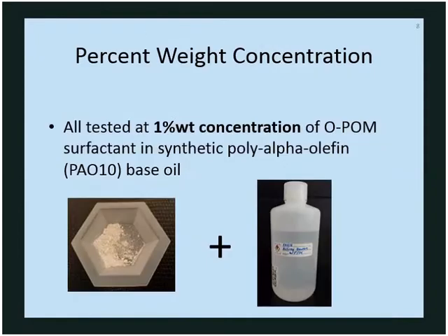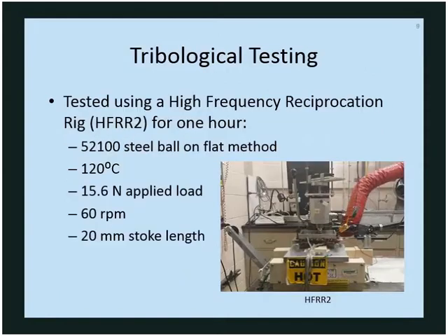Varying percent weight concentrations were used. However, they were all tested at a 1% weight concentration of OPOM surfactant in synthetic polyalphaolefin base 10 oil. Tribological testing was done, and tribology is the study of friction, lubrication, and wear, particularly within engine systems. And that was done using this high-frequency reciprocating rig for 1 hour using a steel ball and flat in a back-and-forth motion.